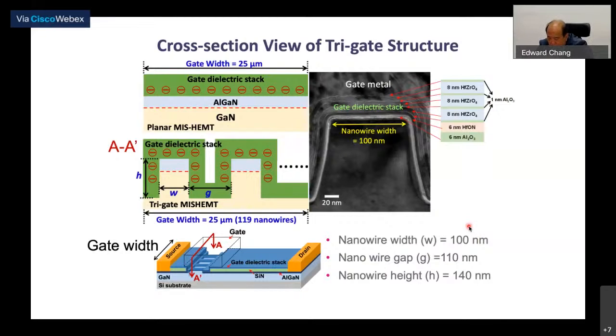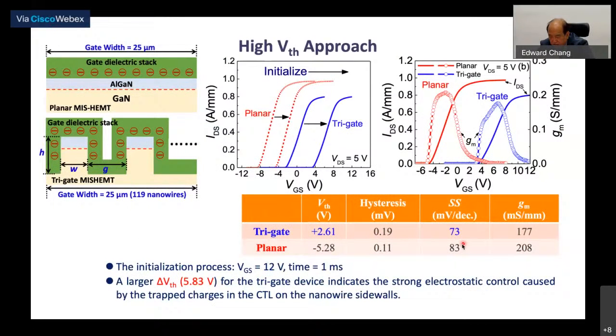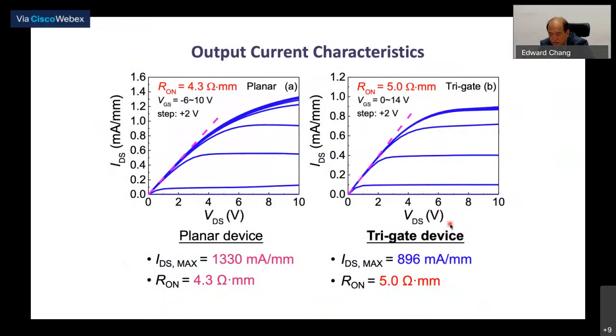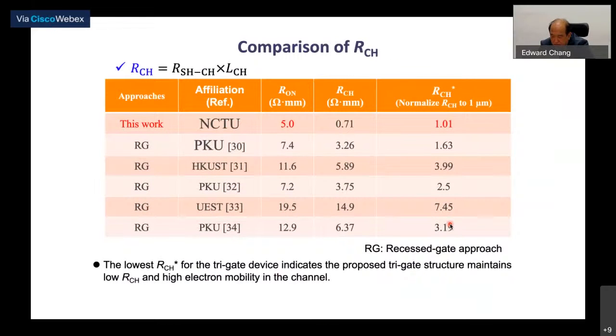This is the cross section. The wire width must be 100 nanometer or less. And this is the tri-gate device performance. You can get the VTH, and the important thing with this approach is that your channel resistance is really reduced, so you get all the characteristics you want for an E-mode device. This tri-gate device has 896 milliamp per millimeter and very low Ron. And this is the comparison of the device with any published data on this kind of HEMT devices.